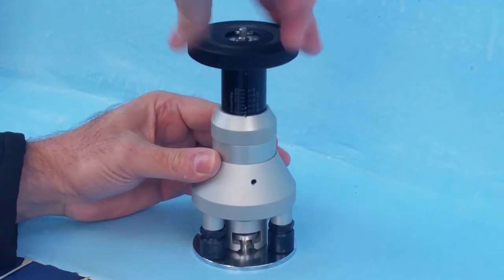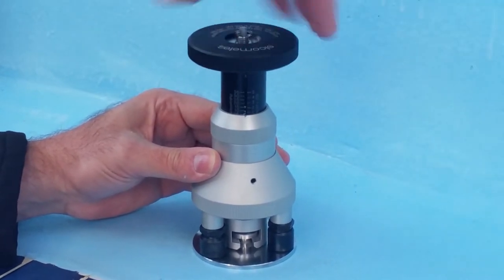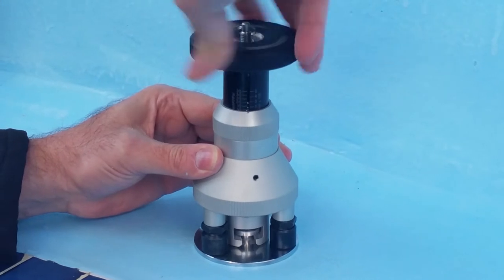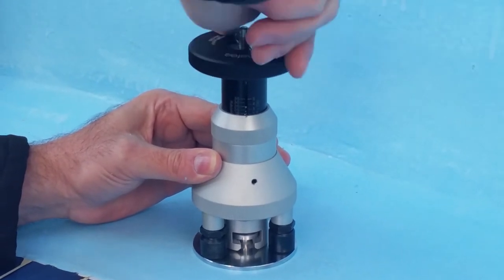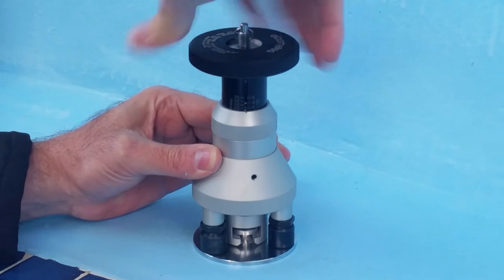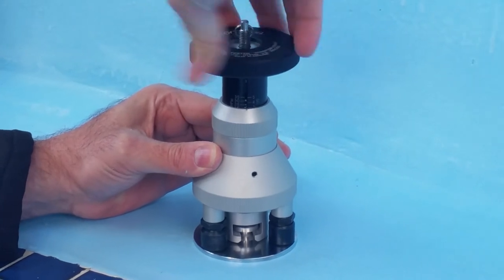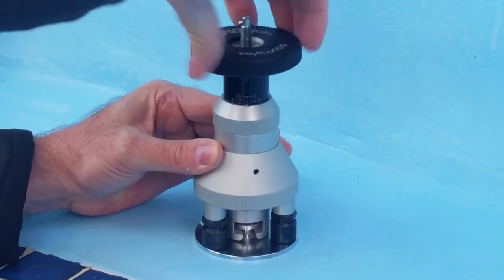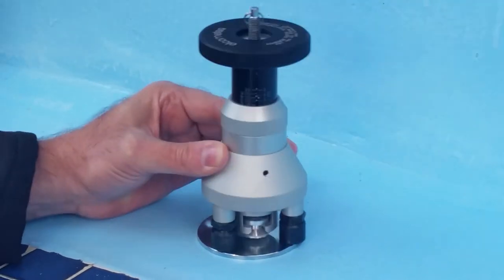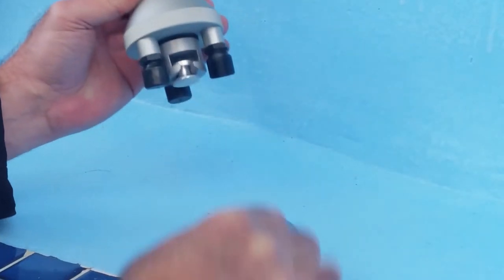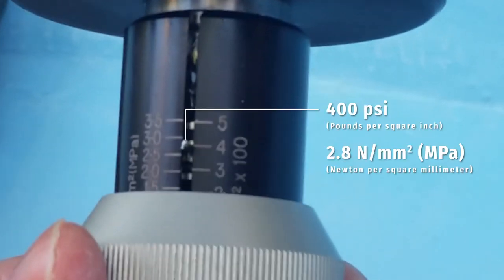We are turning in the knob here until that coating will pull off from the substrate, and we're reaching 400 psi as you can see there, or almost 3 newton per square millimeter. And there it goes. The dolly pulled off with the coating, and the measurement pin has settled on 400 psi or 2.8 newton per square millimeter.